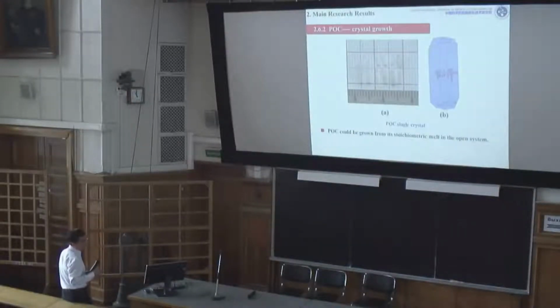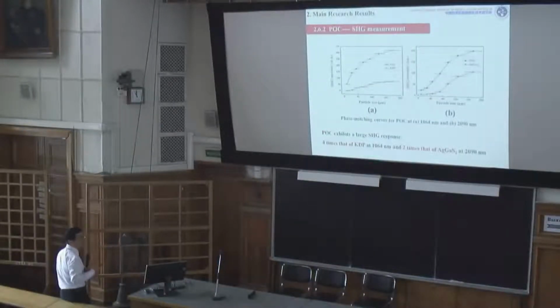And also, we tried to grow some single crystal. We found that it's easy to get crystal in atmosphere from a stoichiometric ratio melt in an open system. It means it's easy to grow single crystal. And also, we measured its nonlinear optical properties. For example, at 1064 nanometer, it exhibits 4 times that of commercial KDP. In the infrared region, it shows 2 times that of AGS, the commercial IR material, at 2090 nanometer. And also, this material is transparent over a broad spectral range from 0.34 to 13.9 micron. It means it can cover 2 important atmospheric transparent windows, 3 to 5 and 8 to 14 micron.